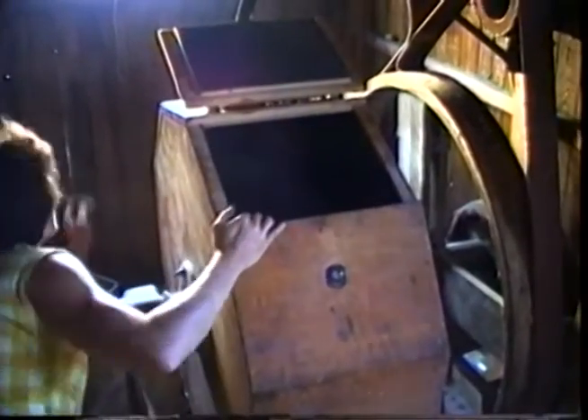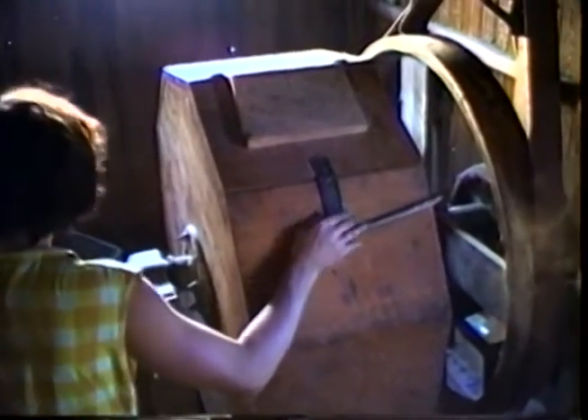This wooden drum tumbles the beads to separate the excess from the edges. They use sieves to separate out the beads to go to the factory for further polishing. Small beads can be fire polished. The scrap is also collected to be remelted.